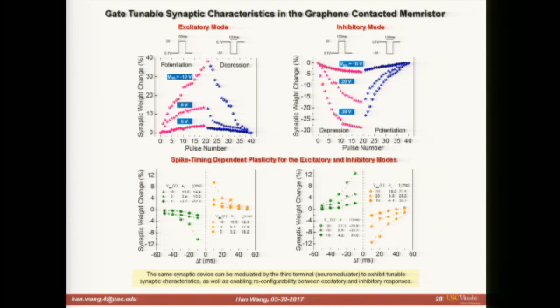When the gate bias becomes 0 and slightly positive, it starts to suppress this filament formation, so the response becomes much lower. When the gate bias becomes very positive, the gate field will dominate over the bias field, so you get inhibitory responses.